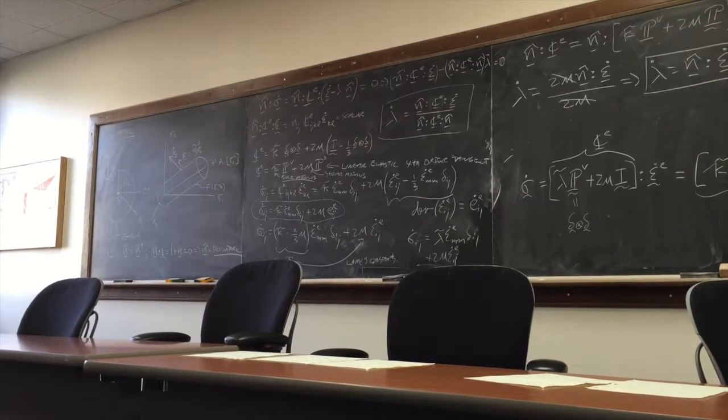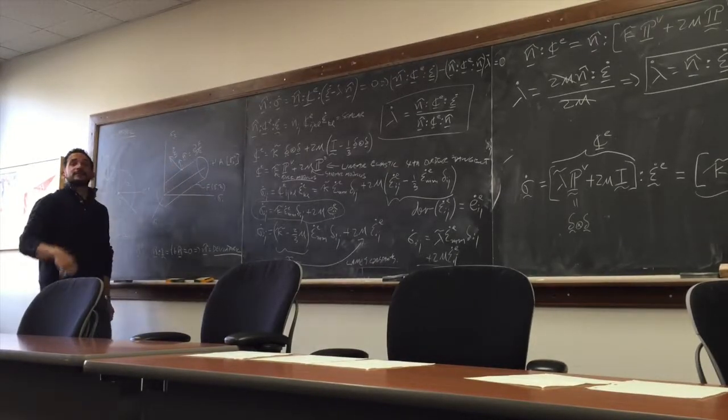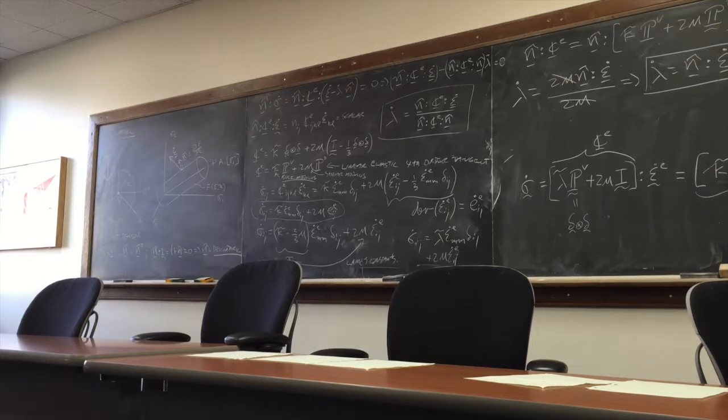So for instance, if epsilon dot is what? Can you think of a physical strain increment that will always be orthogonal to n hat? Hydrostatic. Volumetric or isotropic, right? So if you happen to be here, you were on the yield surface, you were at plasticity, and then all of a sudden your subsequent strain increments are nothing but volumetric, then your plasticity will say your lambda dot will be 0. That's a special case. And F is 0. Then and only then, in that non-trivial case, you will get this condition with lambda dot, you see.